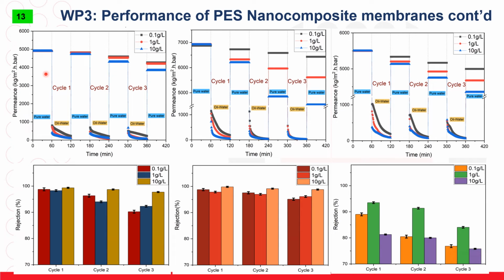And as can be observed, this is for the unmodified membrane. Its pure water permeance dropped from around 5,000 to around 4,000, whereas for the hydrophilic membrane, the pure water permeance was relatively high for the low concentration oily wastewater. And as can be observed, the hydrophobic membrane had a stable performance, but of course it had a low pure water permeance.